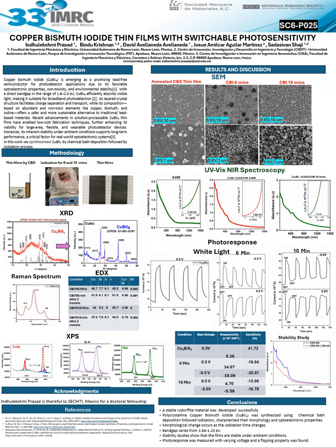After that, when we iodized and obtained the film of copper bismuth iodide and analyzed it on XRD, we found a cubic phase having a stoichiometry of CuBiI4. For confirming the phase we did Raman analysis, and we got 3 active Raman modes, and we confirmed that it is the phase of CuBiI4.